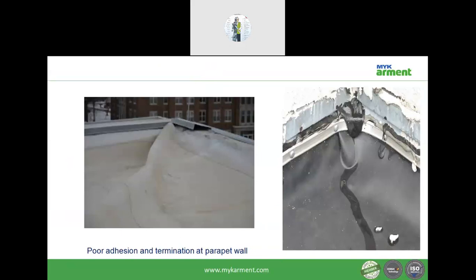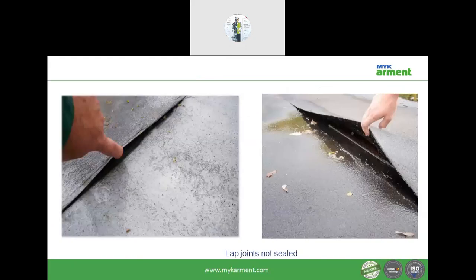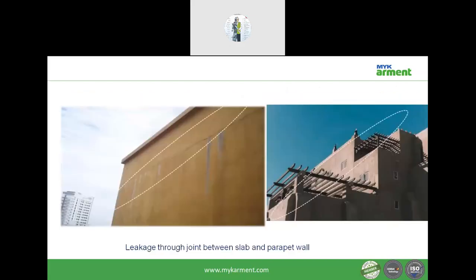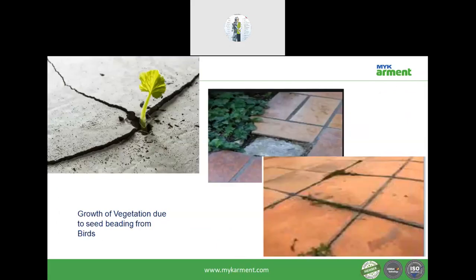Sometimes what happens is, if these waterproofing agencies are not technically clear about a certain kind of waterproofing system, they do such a negligent job that would compromise the quality of the system. Now, the lap joints are not sealed properly. This is another problem when you use sheet-based membrane systems. Another issue you find is leakage through the joint between the slab and the parapet. This is another problem where you can see water seeping, and efflorescence and leaching effects take place.